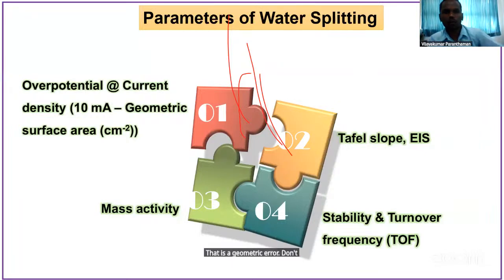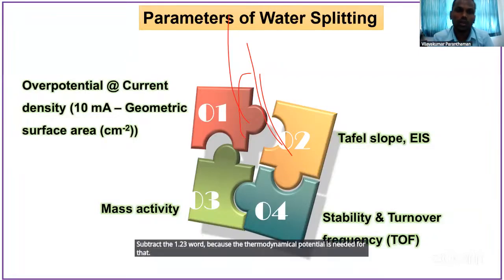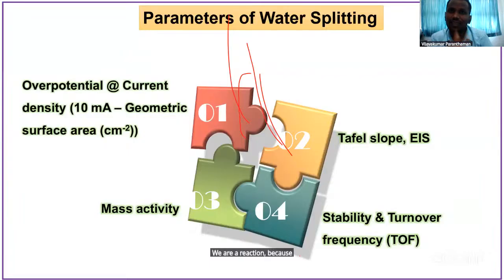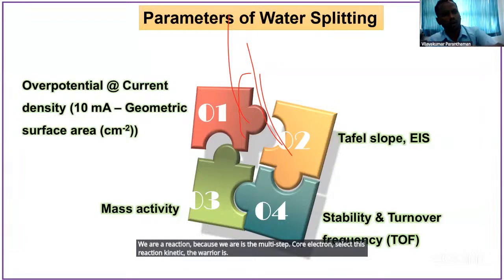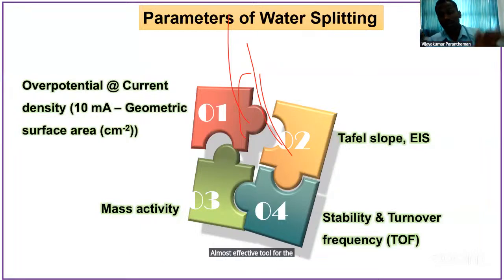Don't confuse geometric area and electrochemical active surface area. So they depend upon the geometric surface area. We have calculated the overpotential. If you are doing an experiment on OER, you must subtract the 1.23 volt, because the thermodynamic potential is needed for the OER reaction, because OER is a multi-step, 4-electron reaction with sluggish kinetics. The OER is an effective tool for metal-air batteries and water splitting technologies, and battery applications too. So these are the important parameters we have to optimize.